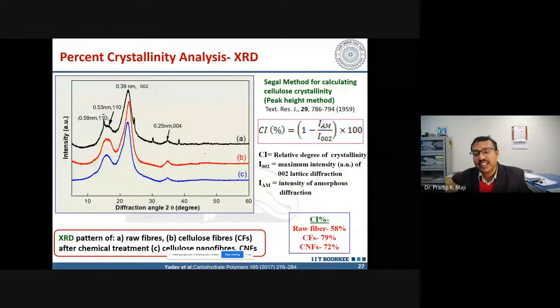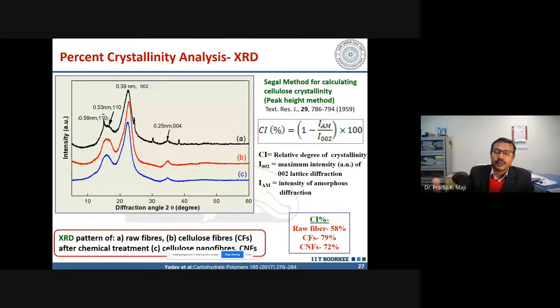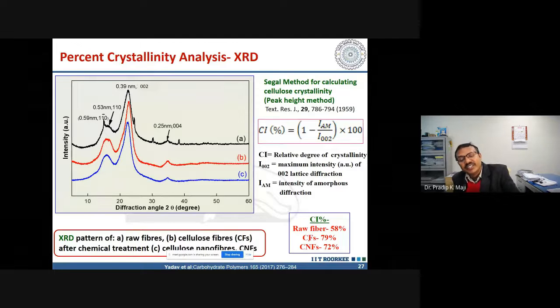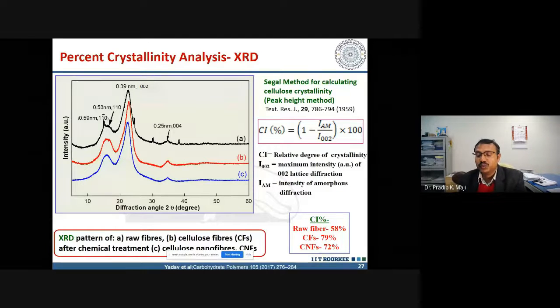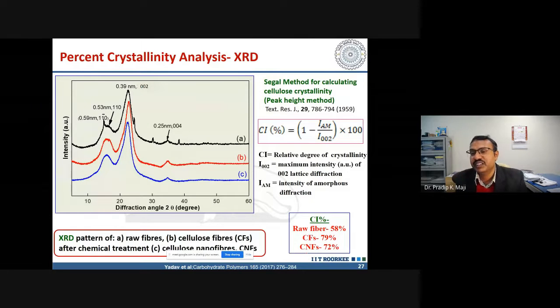Now percent crystallinity - whatever result I am showing here is for the cellulose nanofiber. If you see raw fiber, it's 58%. Cellulose fibres after chemical treatment is 79%. Cellulose nanofiber after ultrasonication is 72%, because reprocessing by ultrasonication reduces the crystallinity. That's why going from cellulose fiber to cellulose nanofiber, a little reduction in crystallinity has been noticed.